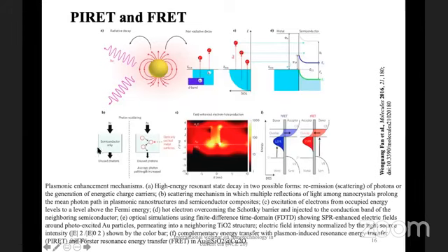So if we take only pure semiconductor and shine a light onto it, it will excite, and some of the light will pass through it without exciting some photons. But if we have nanoparticles in it, then most of the light will remain in the semiconductor. Some is absorbed by the semiconductor and some is being scattered by these nanoparticles or absorbed by the nanoparticles to excite the plasmons, and a very small amount of this light will pass through it. So what happens is, when this light is absorbed by the gold nanoparticles, it will produce hot electrons, and these hot electrons can have energy higher than the barrier energy of the semiconductor.